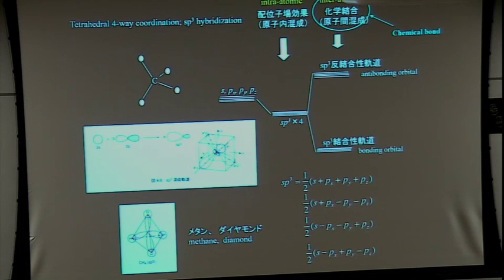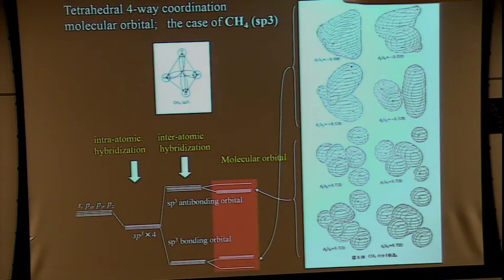Such a profile of molecular orbitals occurs in methane, diamond, silicon and germanium. So the origin of semiconductors and the semiconducting gap corresponds to the bonding and anti-bonding gap. This is an example of the molecular orbitals of CH4 methane. It is still highly symmetric because the carbon in tetrahedral coordination has good symmetry, so the lowest molecular orbital is non-degenerate and the other three orbitals are degenerate.